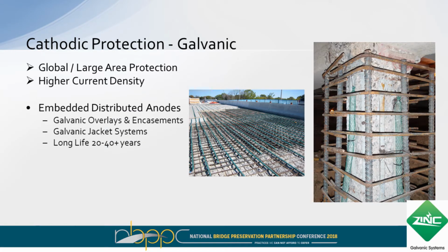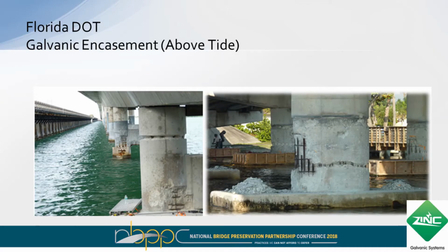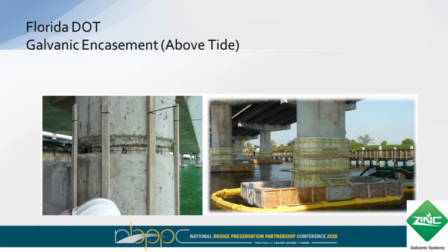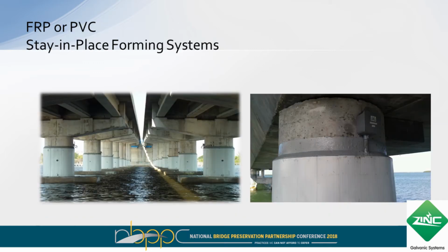You can also use those types of anodes just for column jacketing and concrete jacketing. This is a new cage of steel placed around an existing column with anodes placed within. One other thing here with regard to distributed anodes, just to show a picture of a project in Florida. These are basically columns that are out of the water. So these are being used as embedded anodes within jackets. Florida DOT has done a couple of these types of projects. This is FRP form with the anodes embedded within the encasement. You can also, in some cases, look at PVC forms.